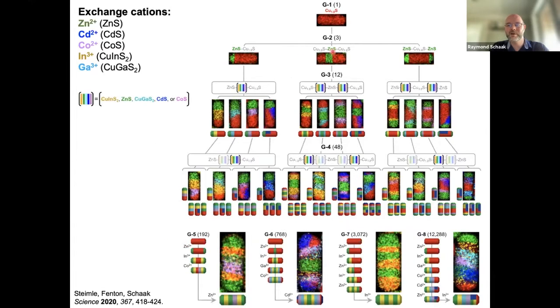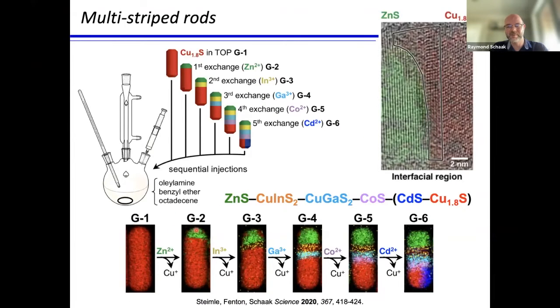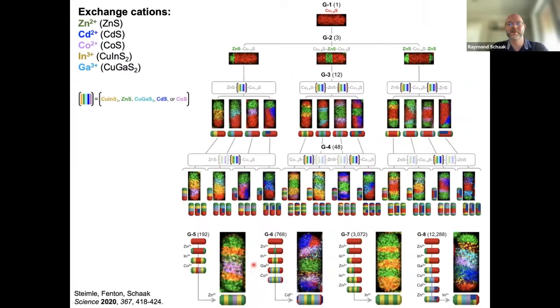But there are conditions where we can also get a central band of zinc sulfide or a double tip type of nanorod. So there are basically 3 high yield samples that we can make through this first step. And if we consider just 5 cations, zinc 2+, cadmium 2+, cobalt 2+, indium 3+, gallium 3+, if we started with a zinc exchange, there are 4 remaining cations from that list. So we can carry out any of these 4 subsequent cation exchange reactions. If we do indium, that's effectively doing exactly what I showed here to make zinc sulfide, indium sulfide, copper sulfide.